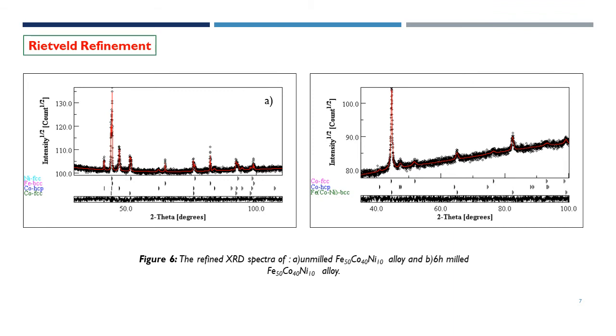The observed anisotropic change in the proportion of the cobalt phases can be associated mainly to the dissolution of cobalt within the iron host lattice and to the allotropic phase transformation of cobalt from the face-centered cubic form to the hexagonal form or vice versa. It was also found that at ambient temperature the cobalt face-centered cubic phase is metastable, but it becomes unstable when it is subjected to mechanical or thermal energy. Thus, the atoms of cobalt face-centered cubic phase diffuse toward the cobalt hexagonal phase due to the high energy generated through milling.